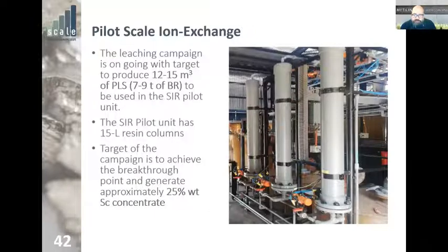This pilot plant has 3 15-liter resins. Our goal is to reach the breakthrough in one of these resins and produce the concentrate having close to 25% weight. At the moment, we have done the leaching and we are currently in the first days of passing our solution through the resin. So unfortunately, I don't have results for you yet, if we will get to the 25 or not. But I can tell you that we are very close in the concentration targets that we set out to get. And we have leached by now almost 10 tons of bauxite residue.